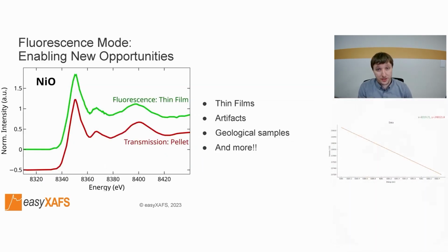As an example of this fluorescence mode performance, we have Zane's measurements on a few 100 nanometer thin film of nickel oxide versus a nickel oxide pellet that we measured in transmission mode.